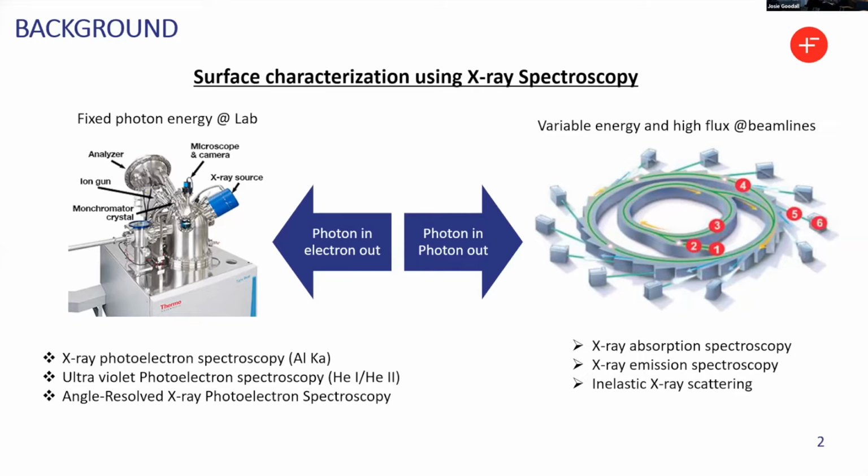But the main issue that we need to address is UHV. So we either need to engineer materials that are stable in UHV, or we need to use materials that can be used straight away in UHV. And for electrochemical processes, electrolyte is one of the important bits. Standard electrolytes are very much not stable in UHV. So you need to work around that and find new electrolytes that are stable, or use solid state electrolytes.